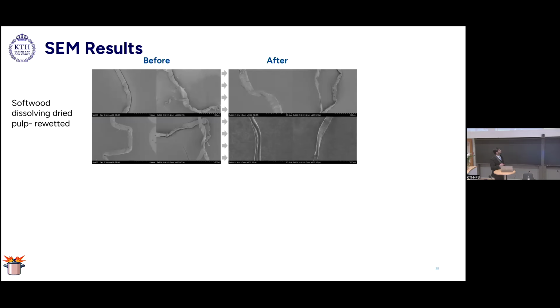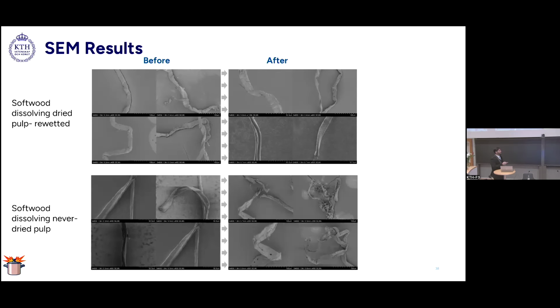on the cellulose fibers. From a visual perspective, the softwood dissolving pulp which was dried and re-wetted was almost unchanged when we treated it with steam. This was expected since, by drying the softwood dissolving pulp, we have pretty much closed all the pores, and the structure is very inaccessible for steam to make any difference. For the never-dried softwood dissolving pulp, it had a little bit less hornification altogether, and steam had a little bit more area to access. In that case, we saw a little bit of surface fibrillation compared to the dried cellulose.